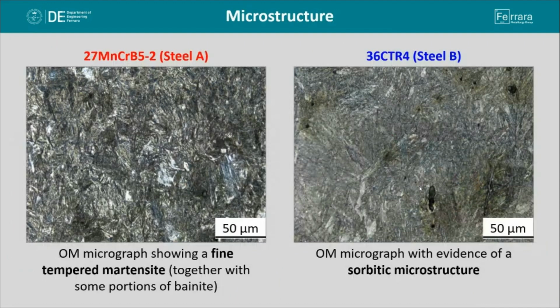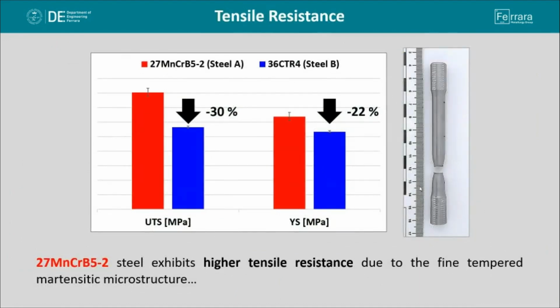So, as concerns the resulting microstructure of the investigated quenched and tempered steels, the first one, so Steel A, exhibits a fine-tempered martensite, while Steel B exhibits a sorbitic microstructure because of tempering performed at higher temperature. Precisely for these reasons, Steel A exhibits higher tensile resistance if we take into account both the ultimate tensile strength and also the yield strength. In fact, tempering performed at higher temperature in case of steel B consisted in a softening mechanism of the material and thus a decrease in tensile strength.